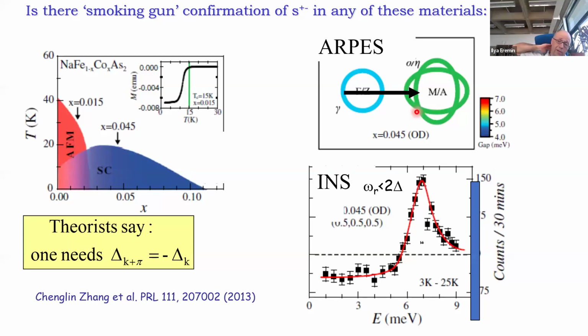So that's a very good question. Let's say in the context of the iron-based superconductors, there is an easy answer. The sign change occurs for large momentum transfer between pockets at the gamma and the pockets at the M point. So the only effectively pair-breaking scattering in this case will be those which scatter from gamma to M due to the impurities.